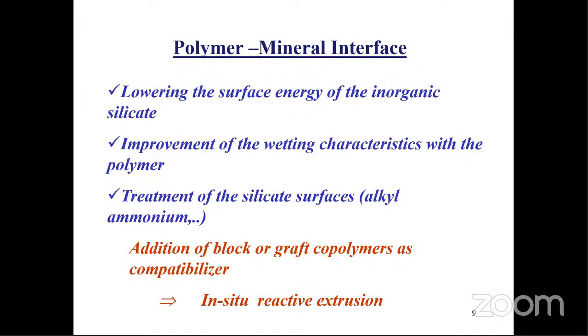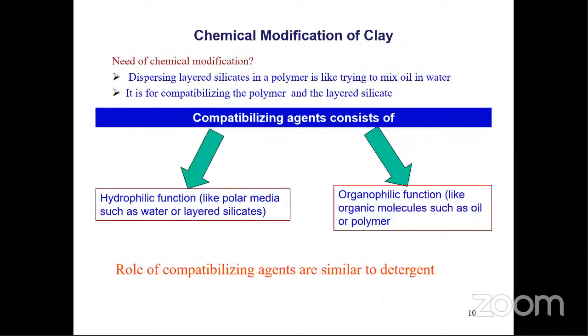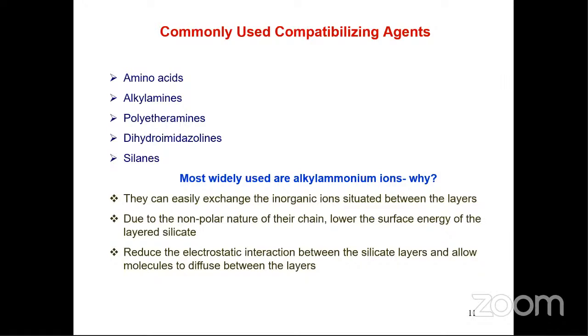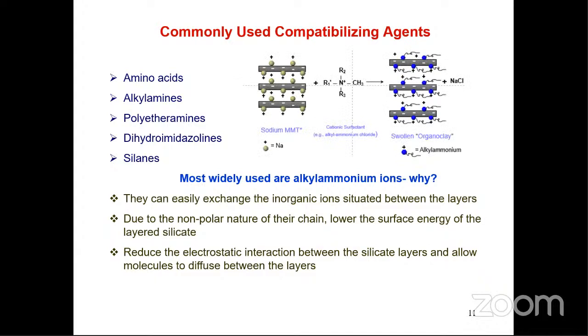My group is very active in making a very strong polymer interface, where we do different things: surfactants, block copolymers, a variety of systems. We do a lot of chemical modification of the clay. We make use of surfactants, compatibilizing agents, amino acids, alkylamines, polyetheramines, and silanes to connect the polymer and the clay surface. Most polymers are hydrophobic. Clay is hydrophilic. So this is our strategy.